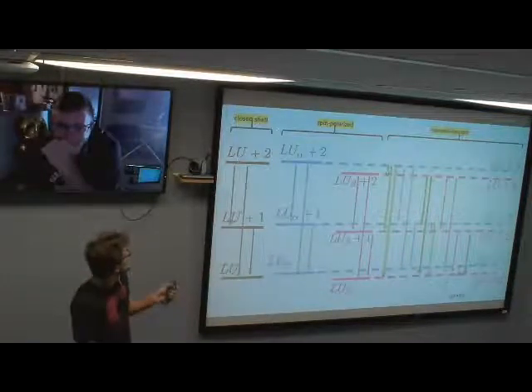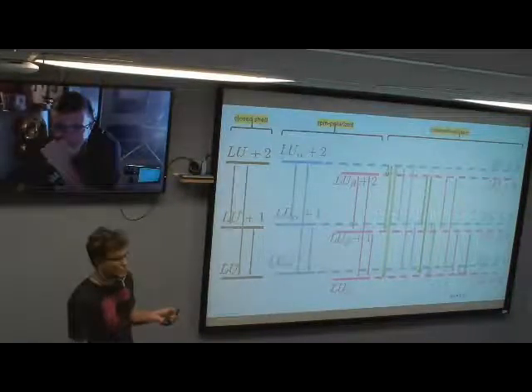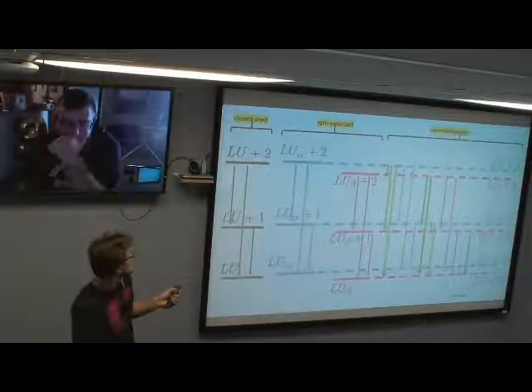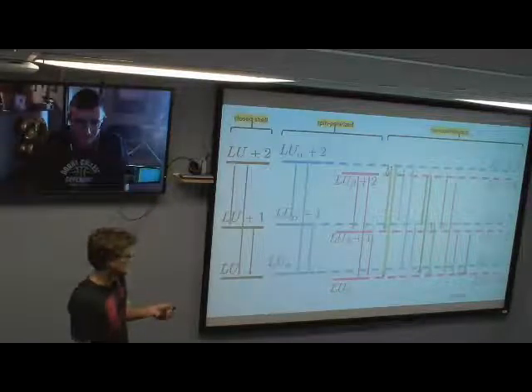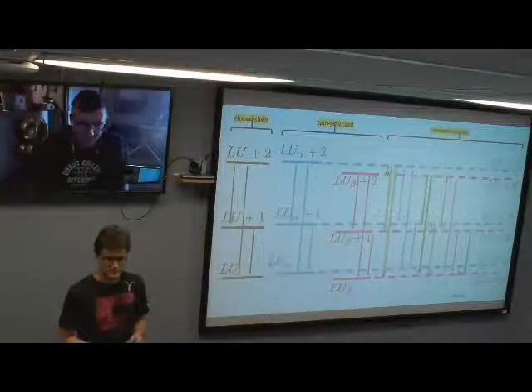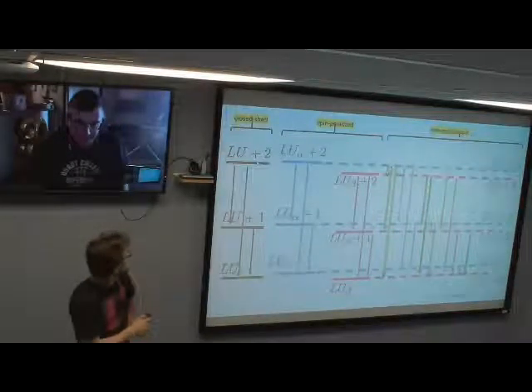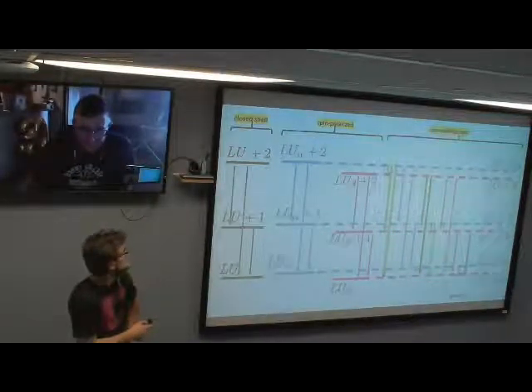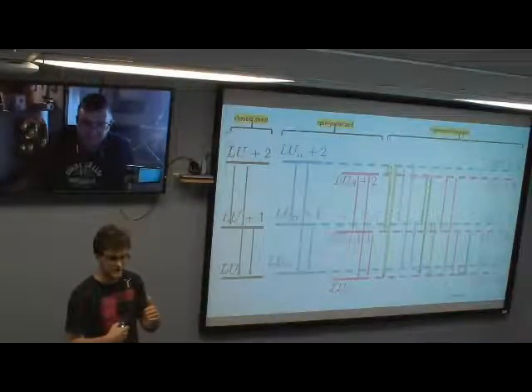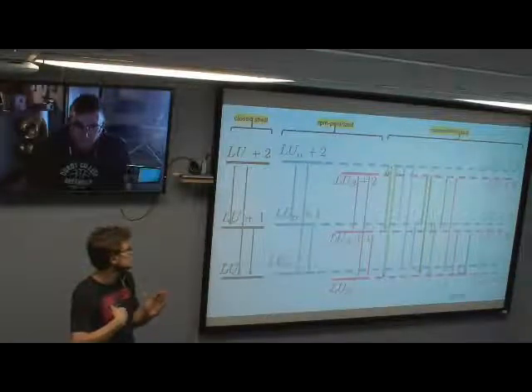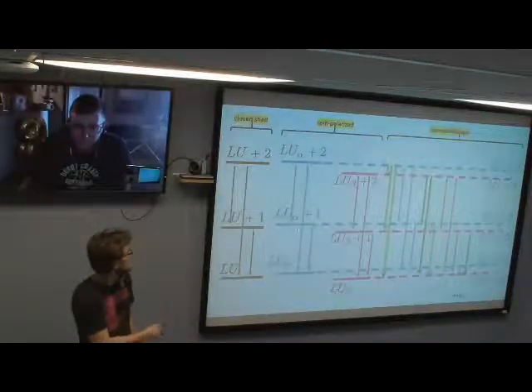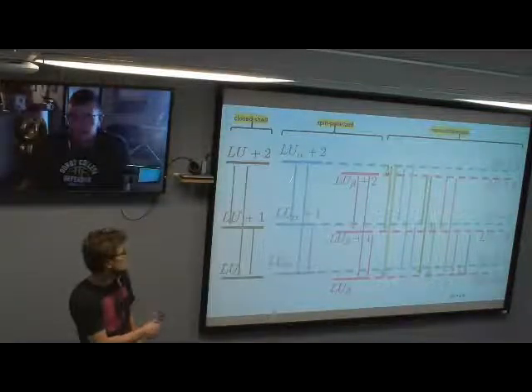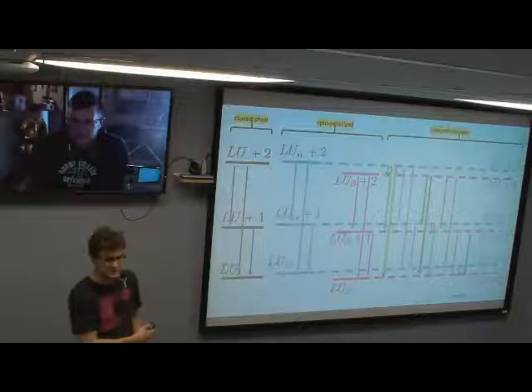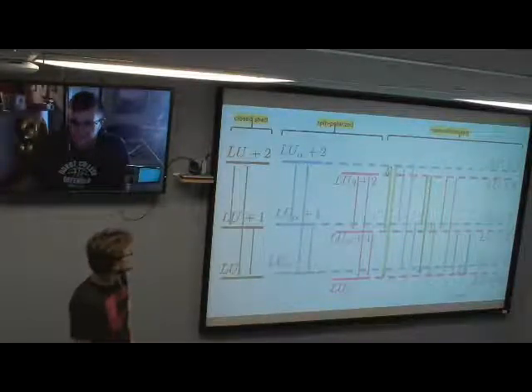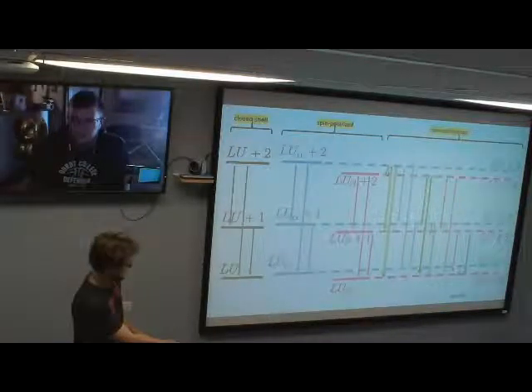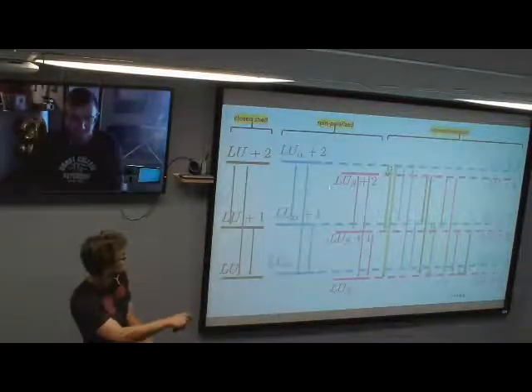For a lot of systems that we work with, they're closed shell. So each state is twice degenerate, doubly occupied. So LUMO+2, LUMO+1 and LUMO are basically the same transitions weighted twice from the VASP calculations. Then we can go into open shell configurations where you have spin polarization, so your up and down electrons can have different energies, but your transitions are only going to be between same spins. So if you have a spin alpha LUMO and it's non-radiatively relaxing, it's only going to go to other alpha states. And the same with beta. You can do the same thing with optical transitions, from HOMO up to LUMO, in both systems.